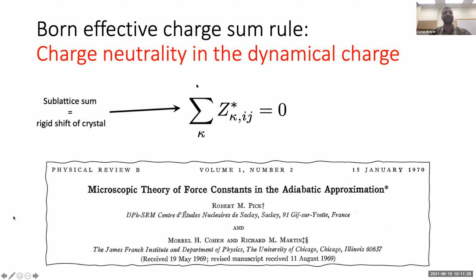And the reason is basically if we sum up over the sublattices, the Born effective charges, what we're basically doing is taking the entire crystal and shifting it. And by the acoustic sum rule, we know that if we take the entire crystal and shift it, we shouldn't change any of its properties. We shouldn't induce any forces. We shouldn't induce any currents. And therefore the Born effective charges sum to zero.